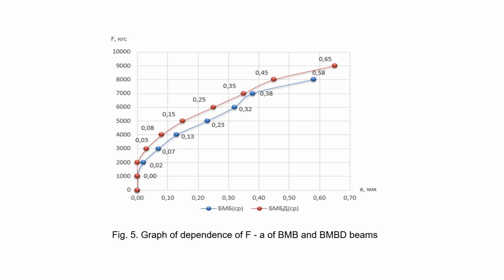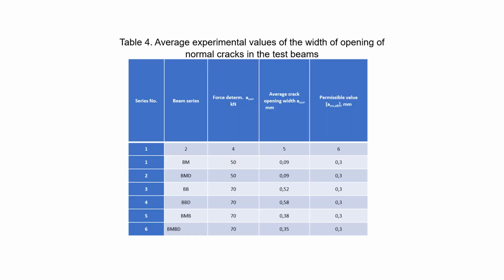The destruction of the beams occurred due to the compression of the concrete of the compressed zone with the simultaneous complete or partial rupture of the BFRP reinforcement fiber. For further analysis of the obtained values of the widths of the normal crack opening of the experimental beams and the limit values according to current standards, Table 4 was compiled.